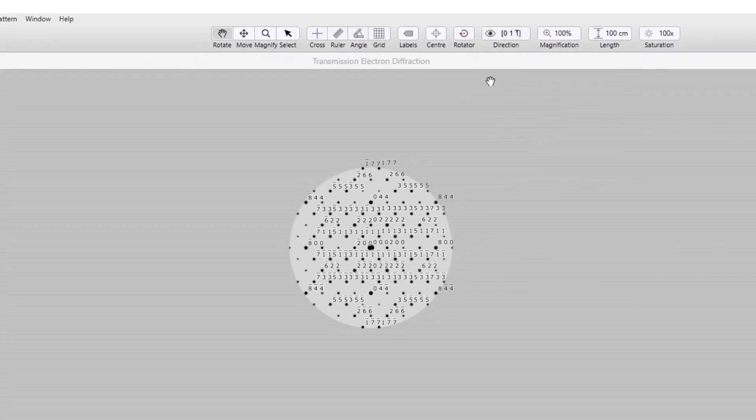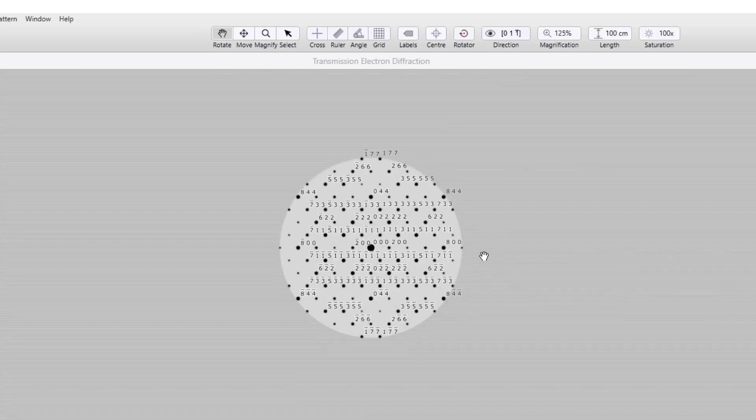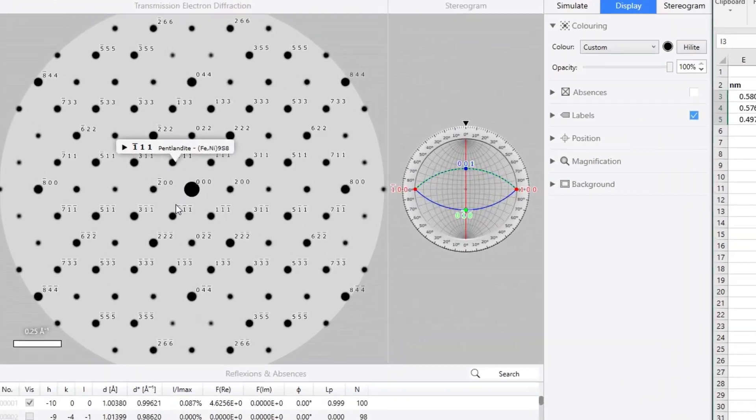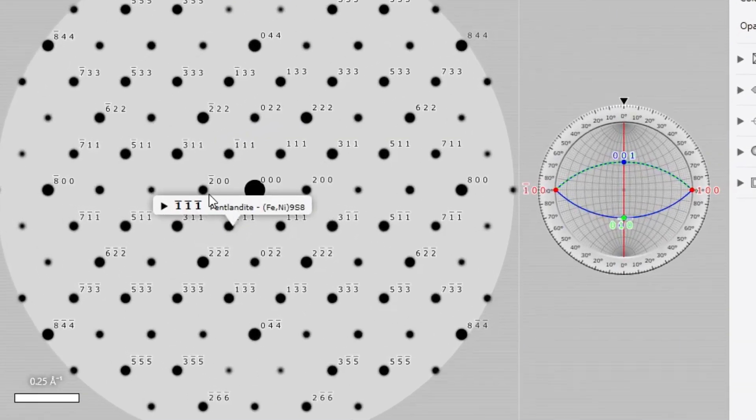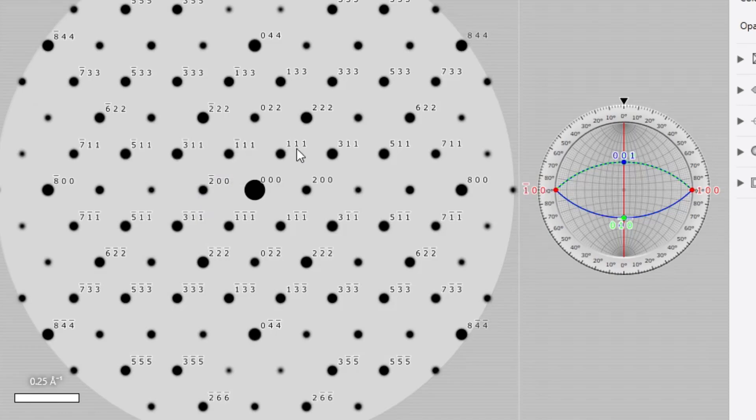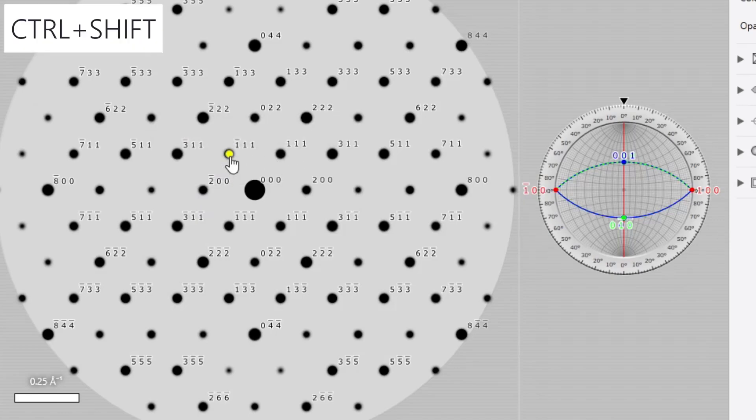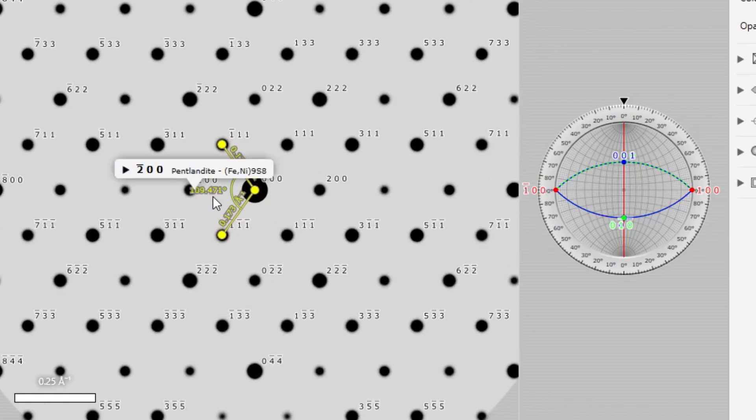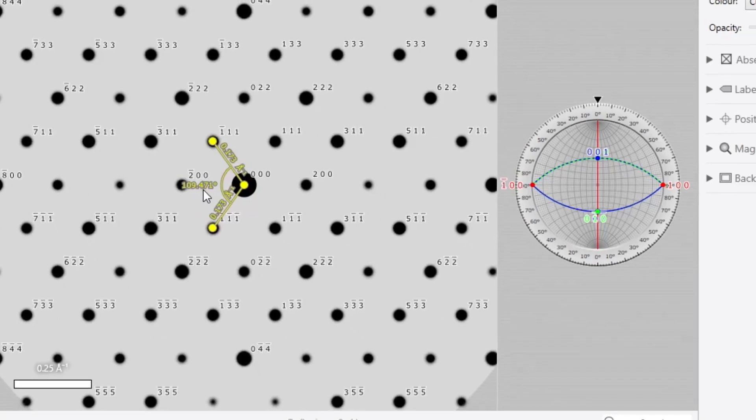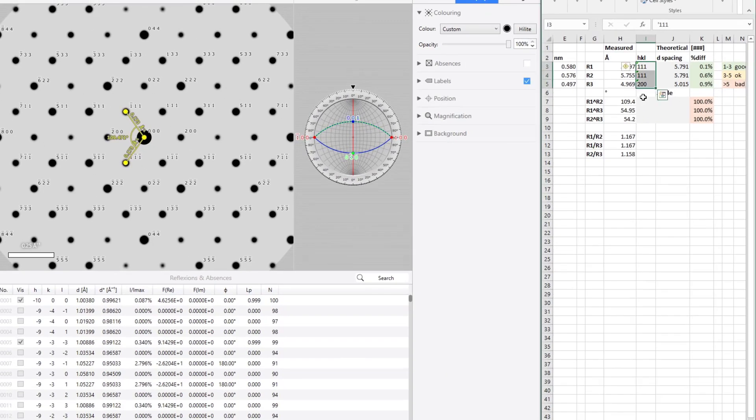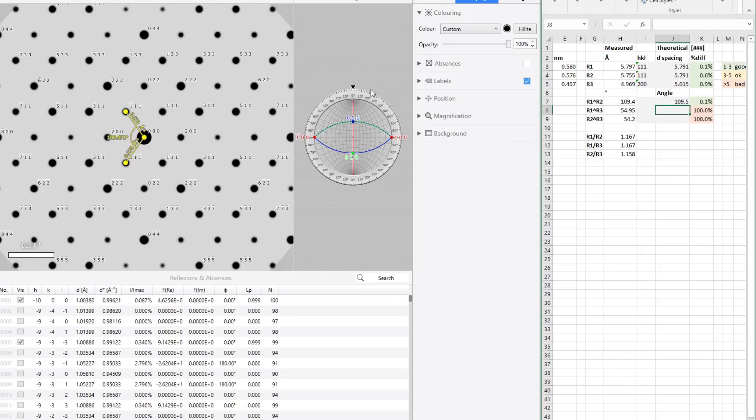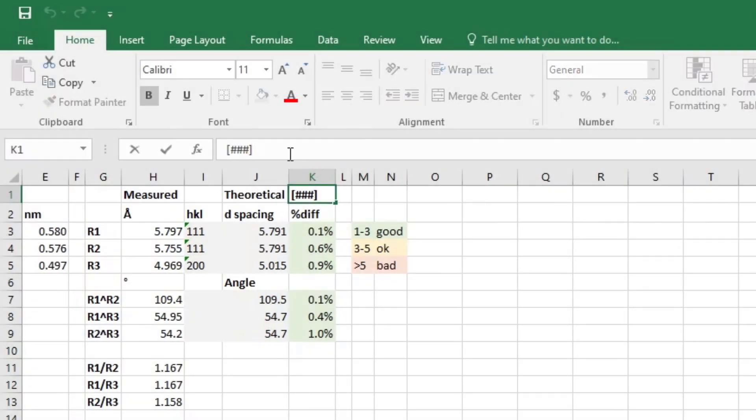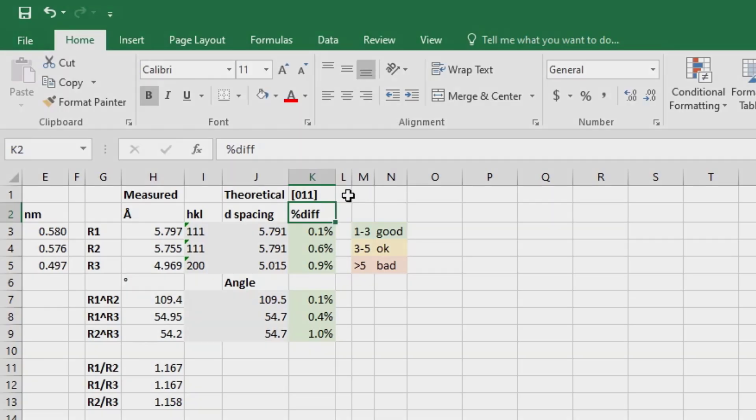I'm using this software single crystal because this will simulate my pattern. Now I can measure the angles based on that simulation. This is the structure for Pentlandite because that's what I believe my mineral to be. If I hold Ctrl-Shift and then left click on my mouse for the three spots, R1, the center spot, R2, that will give me the theoretical angles. In this case, we don't need to measure on both sides because this is a simulated pattern, so it'll be perfectly symmetric. So this is my result. Green means good. I have a percent difference that's pretty good. My match is down the 0-1-1 plane of Pentlandite. Now you know how to index spot patterns.